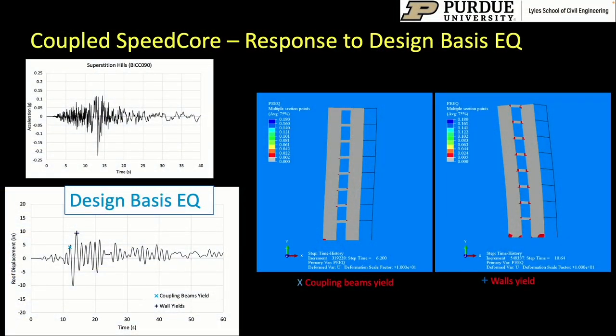But this is just static pushover behavior. So we really wanted to see the behavior of the system under dynamic earthquake loading. So we did a series of nonlinear time history analyses. I'm showing you here the response from one of those earthquakes that we were considering. It's the Superstition Hills earthquake, and you're looking at about an 8-story structure. We scaled the ground motion to be a design basis earthquake, and what we found was that all you were getting was some yielding in the coupling beams along the height and some yielding at the base of the walls, which is what you'd like to see for the design basis earthquake.